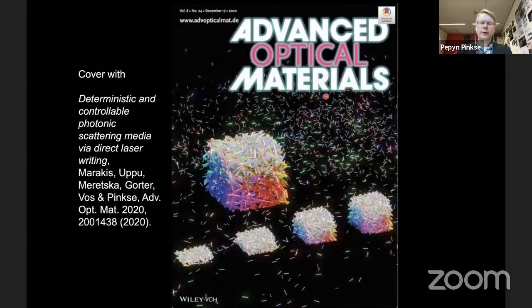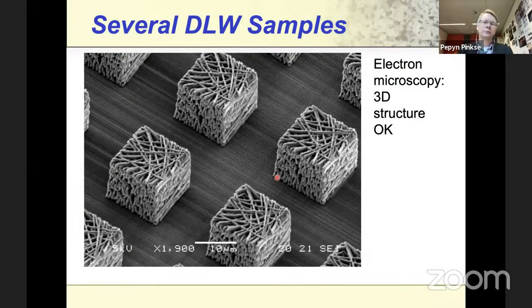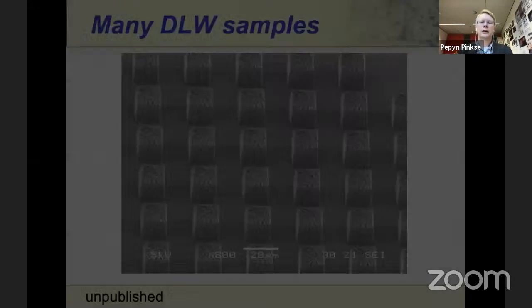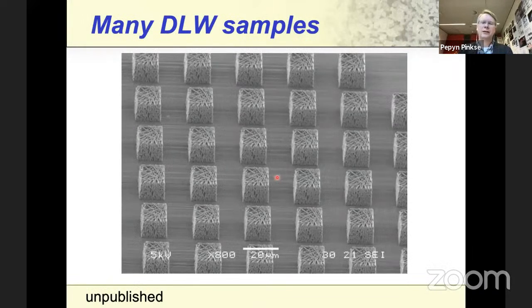Happily, we were able to publish this last year, and the art on this cover is the design file of these cubes. And one trick we did for measuring optical properties is to print a cube at different heights sunken into the substrate, so that you can actually use this to measure the scattering length of this material. So we can make 2 cubes, 4 cubes, many of these. It's just a matter of printing the same file again and again.